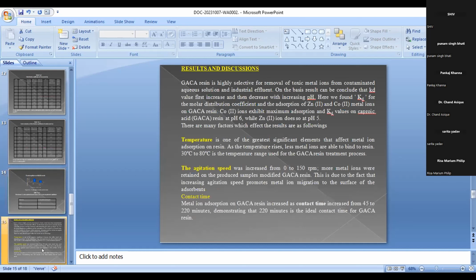Result and discussion: the GACA resin are highly selective for removal of toxic metal ions from contaminated aqueous solution and industrial effluent. On this basis, the result can be concluded that the KD value first increases and then decreases with increasing pH. Here we found the KD, the distribution coefficient, and the adsorption of cobalt(II) metal ions on GACA resin. Cobalt(II) ions exhibit maximum adsorption KD value on the caproic acid reagents at pH 6, while the zinc(II) ions do so at another pH value.